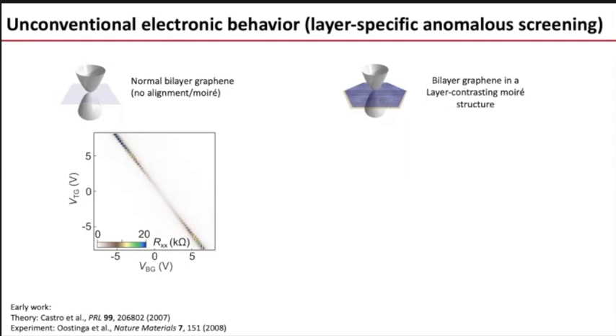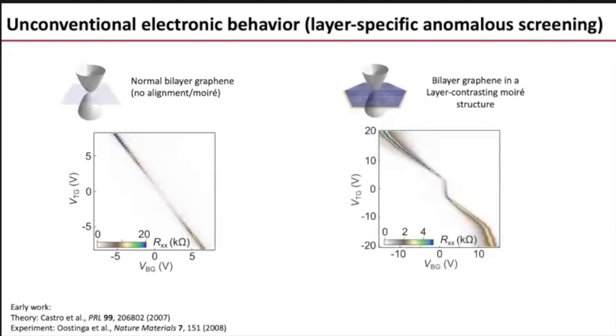So if you do this for bilayer graphene in a layer contrasting Moiré structure, you get this, okay? So you get this region near, in this case, zero, zero, where even though I'm adding carriers to my system, if I sweep the back gate, what I see is a resistance peak. I vary the top gate, I'm adding carriers to my system, but they don't seem to matter, okay? Transport characteristics remain the same. We used to call this, the gate is not working. Like the top gate's not working. We thought it was disconnected because even though I vary it, the characteristics of the system don't change.